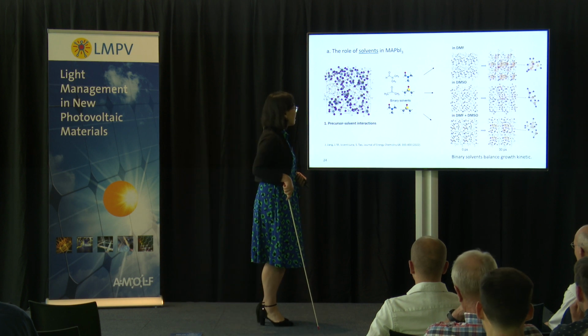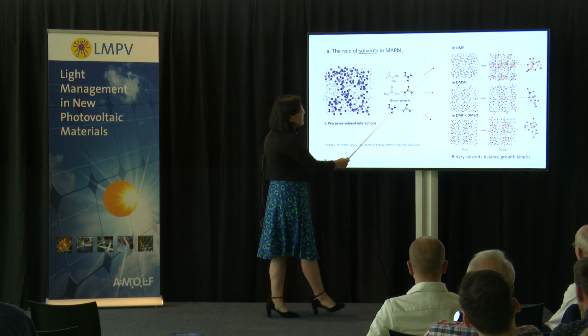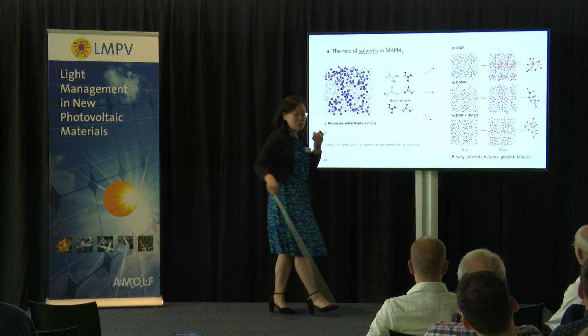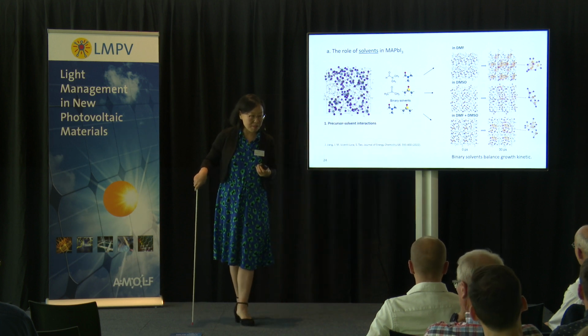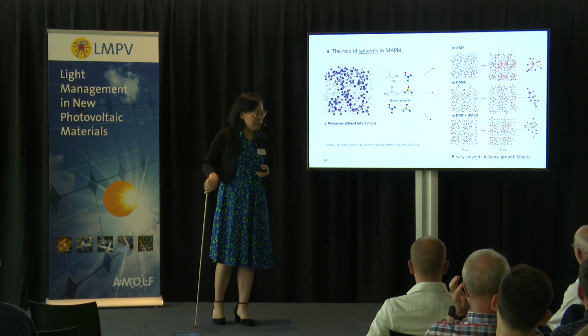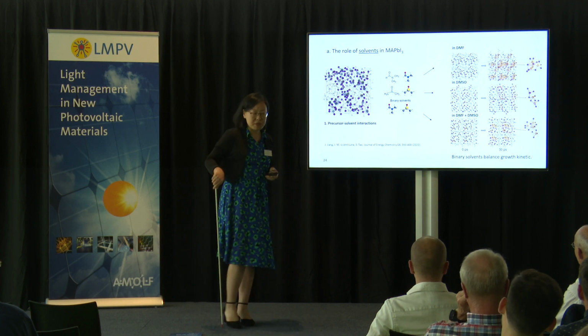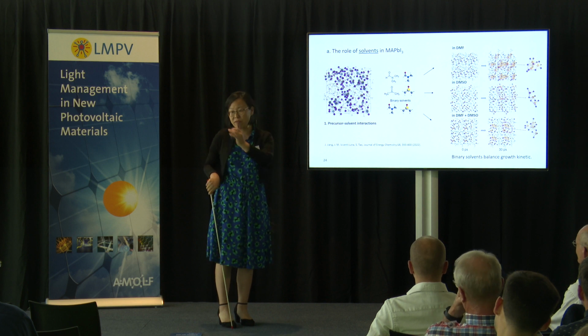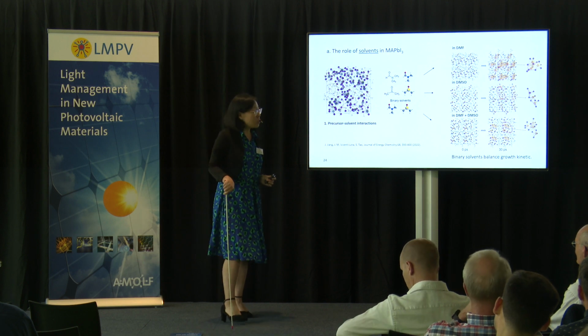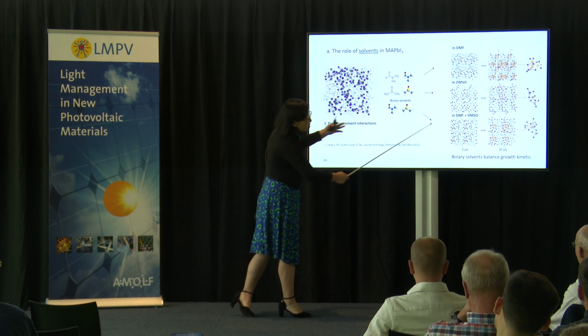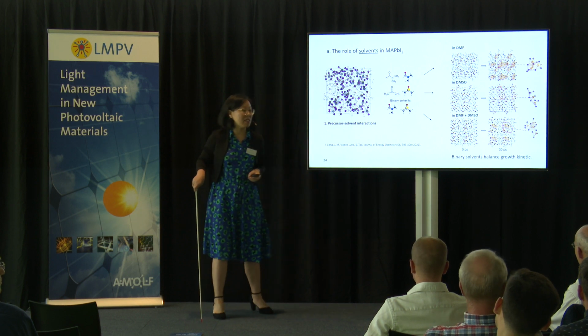By understanding this, we can actually see in DMF, they quickly grow a cluster, but it's not very nicely 3D. But in DMSO, you have the opposite. The bond is so strong, you grow a very small cluster. It does not form 3D. When you mix both a little bit, you just get the best balance in the kinetics.